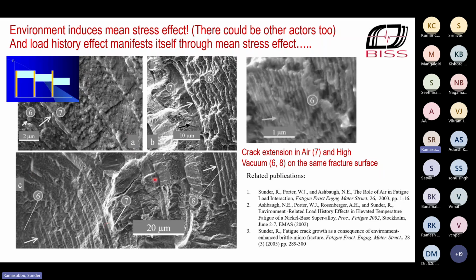But the net result is here to see. This test took almost a month. But at the end of that, when we looked at the fracture surface, here you can see that is the growth in air from left to right. And then when we switch to vacuum, you can see the crack extension is identical in the 3 steps. And this is at an earlier stage when the crack was smaller. In high vacuum, equally spaced steps.